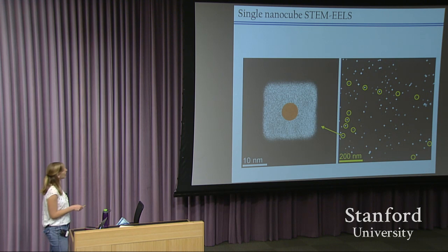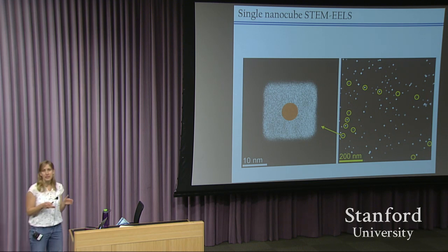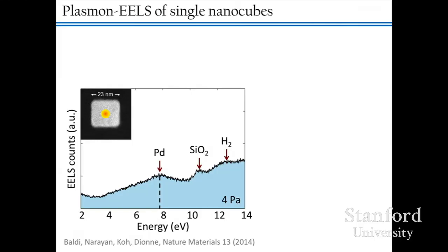And then we spread out the beam to probe about 5 to 10 nanometers across the center of the nanoparticle. And then the electron beam goes through the center of the nanoparticle, and we collect an electron energy loss spectra. So this is basically EELS counts, or intensity, as a function of energy or wavelength.